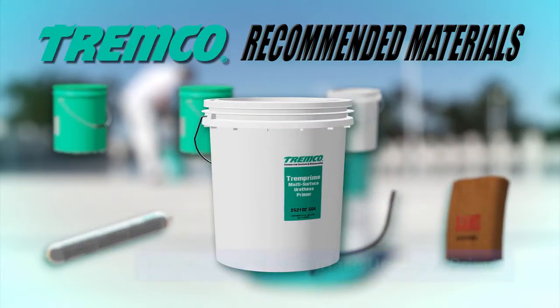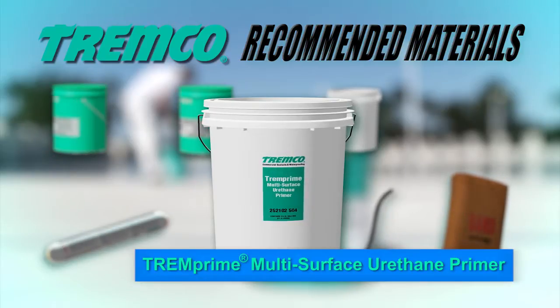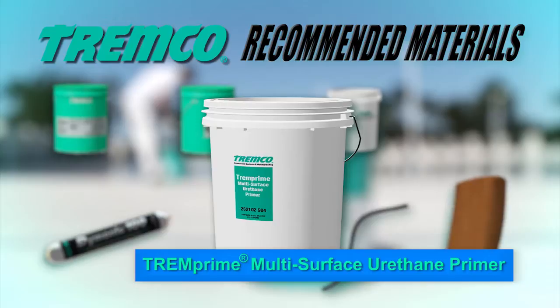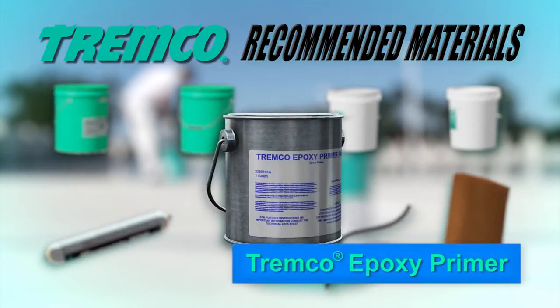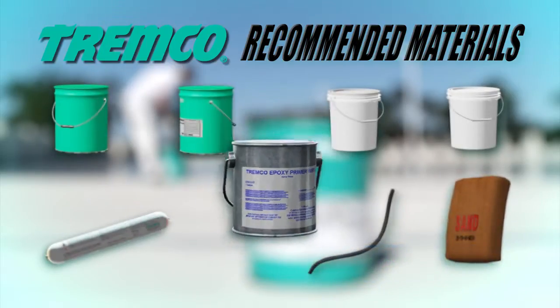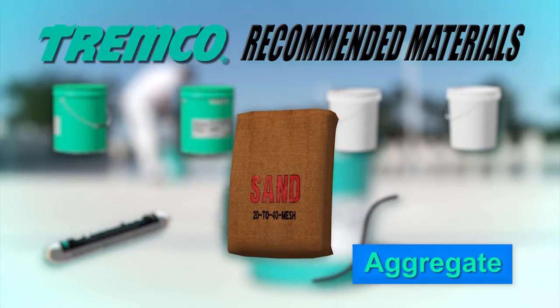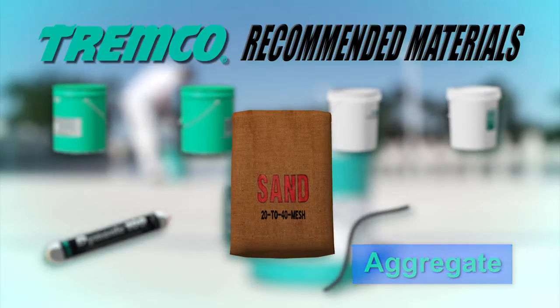Tremprime Multi-Surface Urethane Primer is a VOC-compliant, quick-drying, two-part primer, excellent for use between two layers of urethane deck coating and can be used as a primer on all common construction substrates, including wood, concrete, PVC, and steel. Tremco Epoxy Primer is a two-part epoxy primer that's used with sand to level surfaces before applying the base coat. The recommended aggregate for use with this deck coating system is a 20 to 40 mesh or 0.6 to 0.9 mm diameter silica sand or aluminum oxide, which imparts a textured finish and contributes to wear resistance.